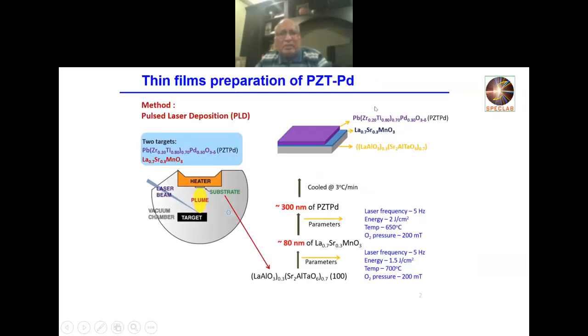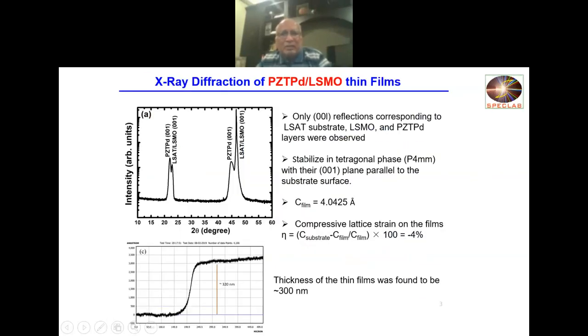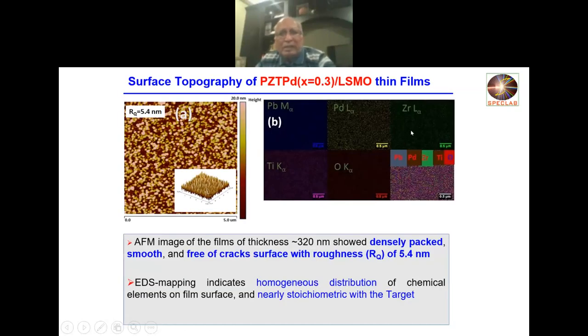Anyway, this is PZT-PD, which is another, instead of PT-PD, we have made PZT-PD. But the results are very similar. I mean, this grows in the same way, but again, you can see that the phases are there, and the film thickness we measured is around 300 nanometers. And again, here, the distribution of various elements is very uniform, that you can see from this EDS data. And here is the AFM data. You can see that the surface roughness is something like 5.4 nanometers in this case.